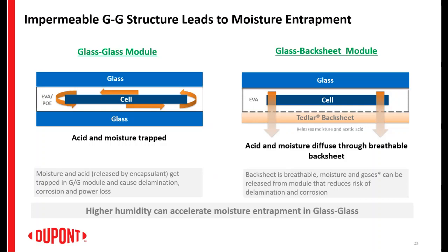So these elements, the moisture and gases or the acids, are never entrapped inside the module, and thus they would not come in contact with metal contacts for long term, which is essentially the root cause of corrosion issues, which eventually would cause faster power loss in the field.